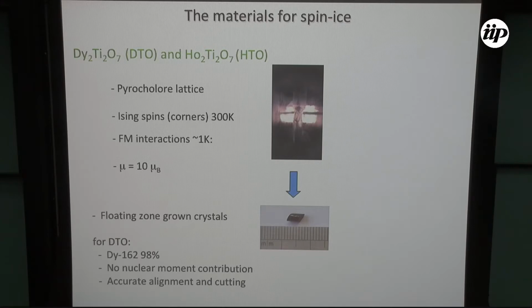If you look at the crystalline structure of dysprosium titanate, you'll find that these are two intertwined pyrochlore lattices, and the oxygens are all around, but only one of them has magnetic moments, and those are Ising spins. This is because of the crystal fields. They are Ising spins to within 300 K, and we're going to be working below 1 K, because the ferromagnetic interactions are of the order of 1 K.